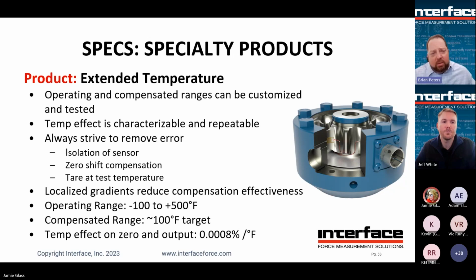We can cover operating ranges from negative 100 degrees all the way up to 500 degrees F. The compensated range is usually around 100 degrees with the flatness of that curve like we showed earlier, and we can shift that cold or hot and move it around depending on your application. But again, remember, we're talking about temp error. Interface delivers very strong temperature performance, usually in the neighborhood of 0.0008% per degree, which isn't a lot. You can't guarantee that from other load cells.